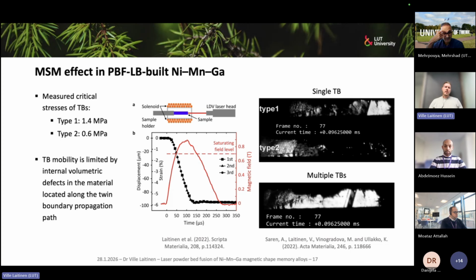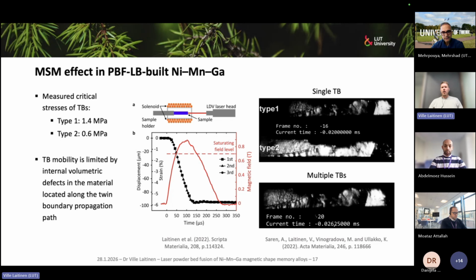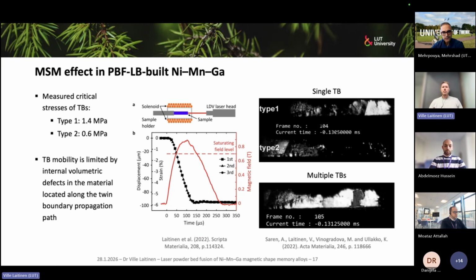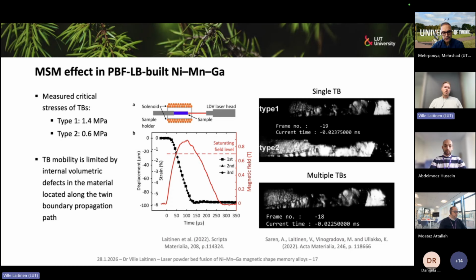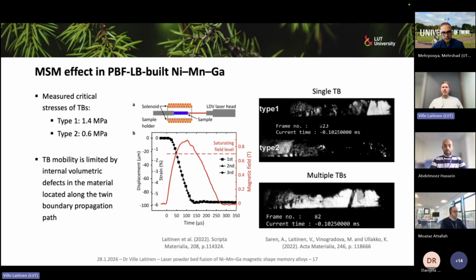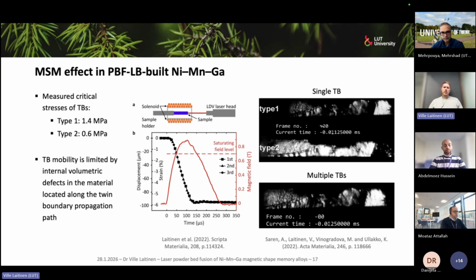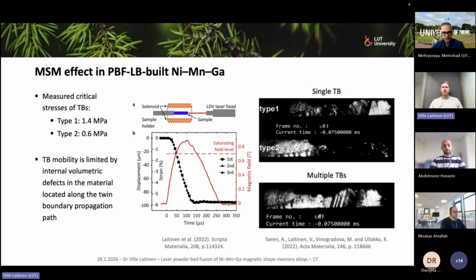But then we also have this bottom case. This is what we would like for an actual actuator, that we have multiple boundaries, ideally hundreds of them. So we have a finer twin structure, and this is more stable. The strain becomes very stable, and we also avoid some critical malfunctions, for example, crossing twin structure, where we have two twins that are tilted in the wrong direction, and they lock themselves into place, and it can actually shatter the sample. So that's something we might do in a post-processing step.